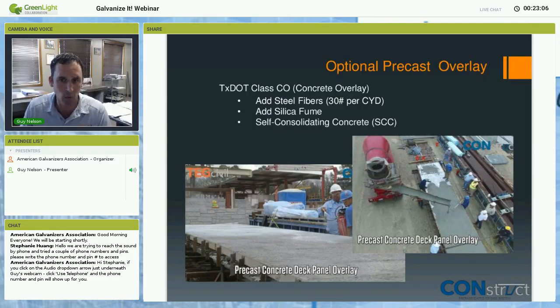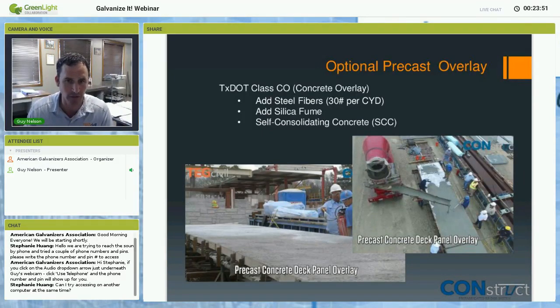In Texas, our standard is to provide a 1.5 inch precast overlay on top of the deck panels. We do that with the standard TxDOT Class CO overlay mix. We also add about 30 pounds per cubic yard of steel fiber, additional silica fume for toughness, and our mix design is a self-consolidating concrete, which flows very easily, flows into all the pockets. We use that to flow into the deck joints between the precast panels, and then finish it as typical with a transverse tining.